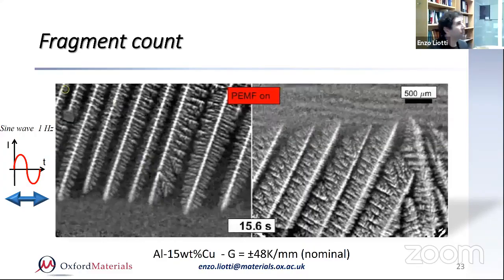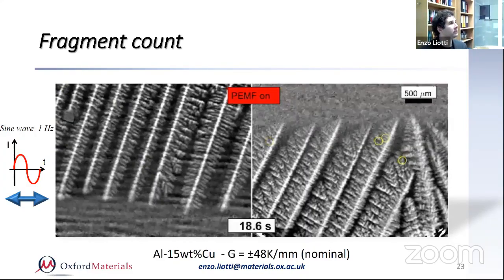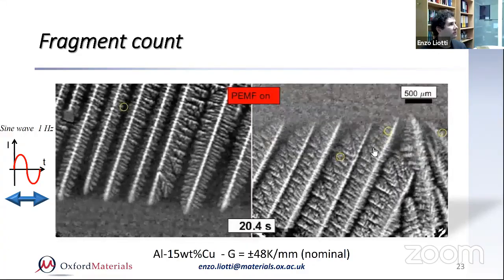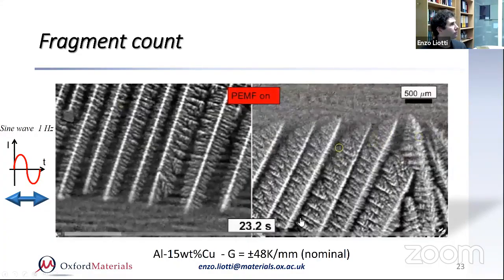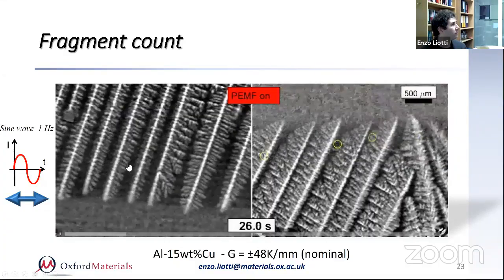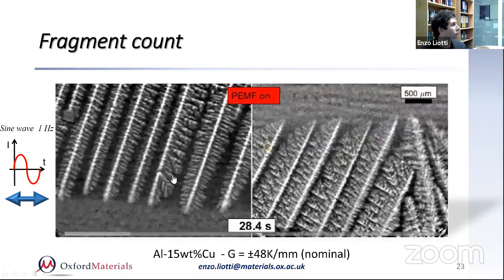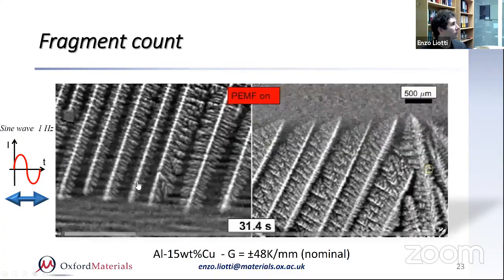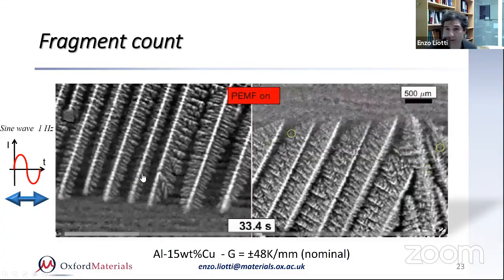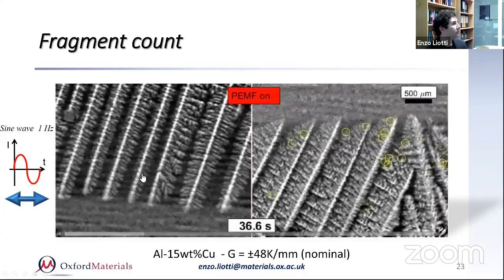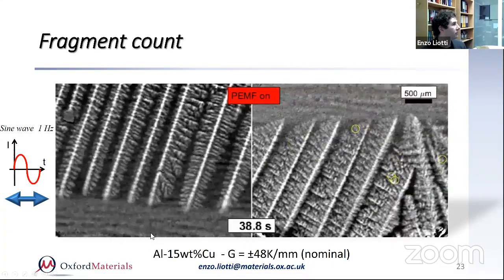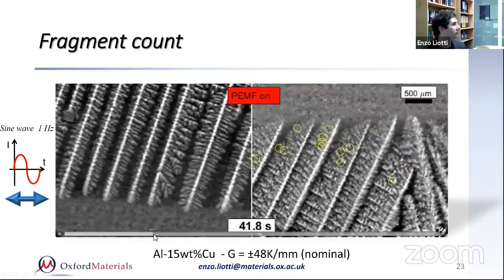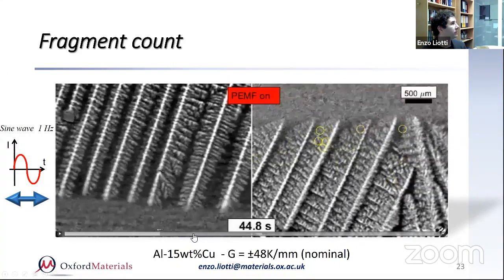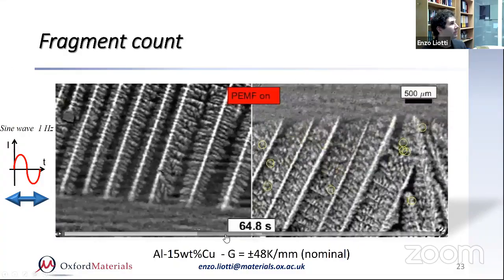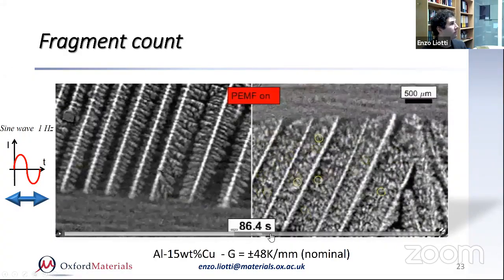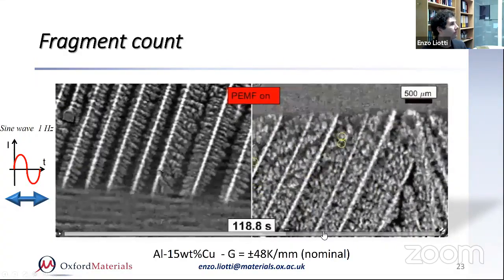And you will see that when they start to fragment, there is normally more fragmentation in the bottom to top than in the top to bottom. And if you notice, the top to bottom are almost oscillating with the flow. So there is a sine wave of 1 Hertz, as you see, and these dendrites are like trees in the wind. Again, I'll speed it up a bit so it's clearer. You see that the fragmentation is increasing. And if I go fast, you can see there is a lot happening in the bottom to top, so the video on the right, and not very much in the other one.